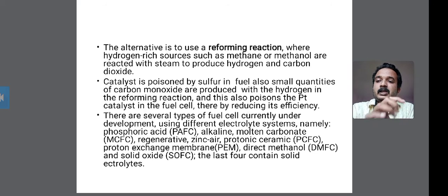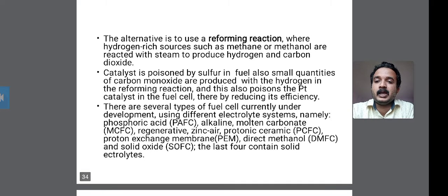A small quantity of carbon monoxide is produced with the hydrogen in the reforming reaction. Therefore the platinum catalyst in the fuel cell is poisoned, reducing its efficiency.